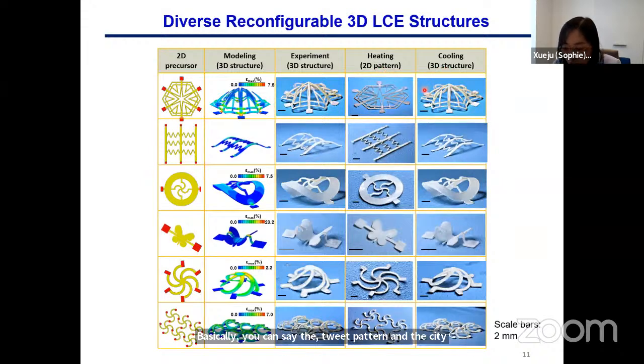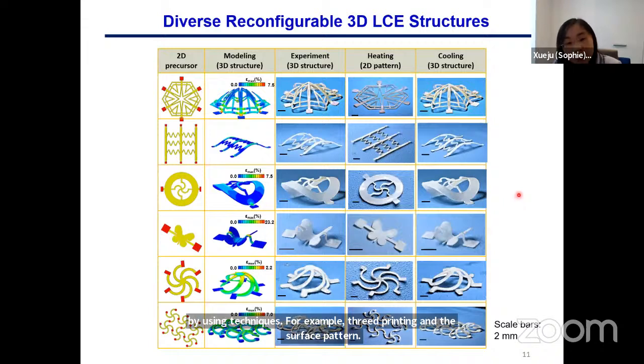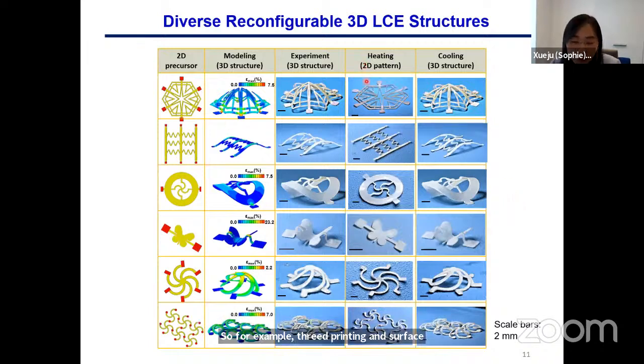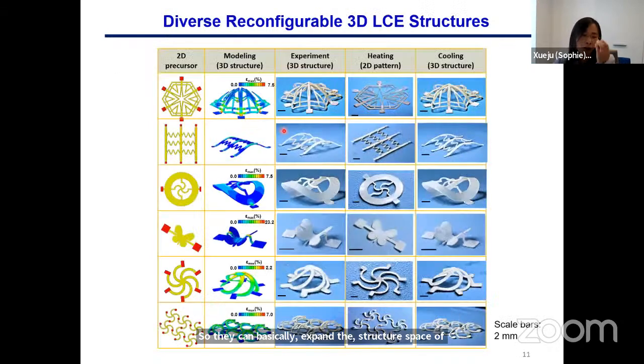So those structures are basically previously inaccessible by using techniques, for example, 3D printing and surface patterning. So they can basically expand the structure space of those 3D LCE structures. Also you may notice that for some structures, even with a small amount of compressive strain, we can enable this mesogen alignment and also can enable the shape morphing behavior.